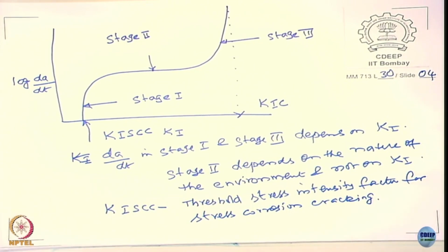Please notice that if we have an environment, if you look at this plot, the crack can grow at a much lower stress intensity level, much lower than K1C.